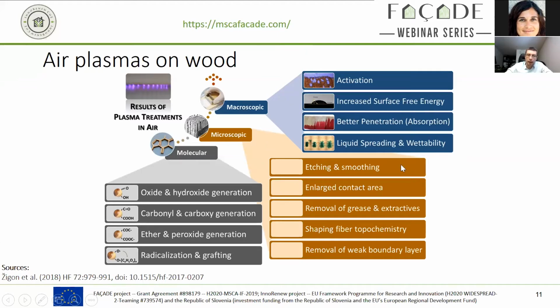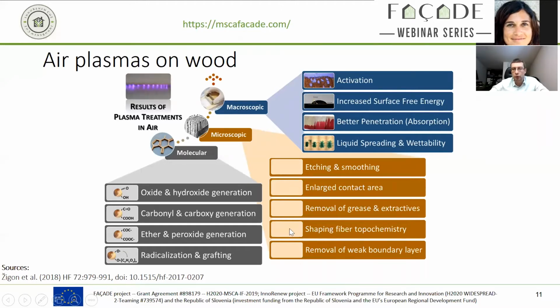Microscopically, we'll often find etching, smoothing the surfaces. We're finding better contact areas with other substances with additional steps that follow after the plasma treatment, like coating or gluing. One thing that we're noticing is the removal of grease, for wood, the removal of extractives, and particularly if we are speaking about fibrous materials, then also plasmas can be used to change the topochemistry of the fibers. On the molecular level, we find functionalization that's generating all sorts of different reactive groups. And so an advantage of the plasma treatments typically is you have inside the plasma all sorts of different reactive species. It provides means for all sorts of different reaction pathways.